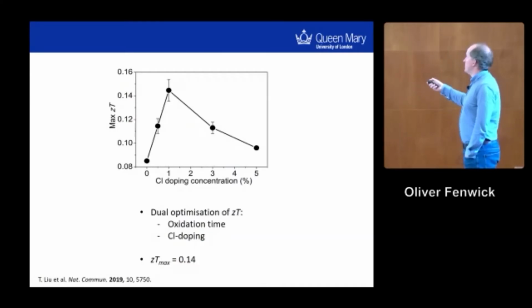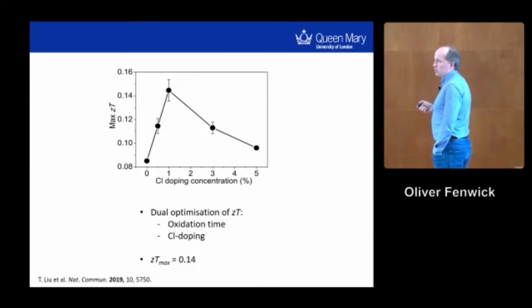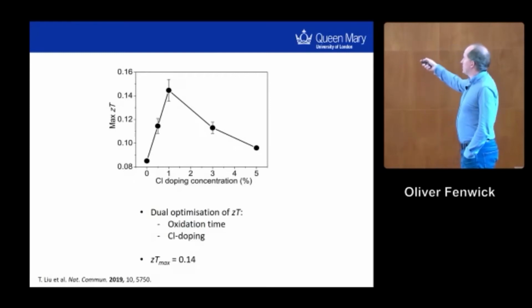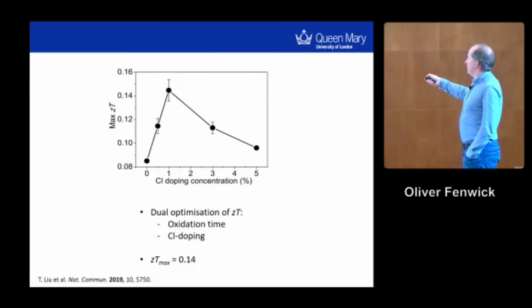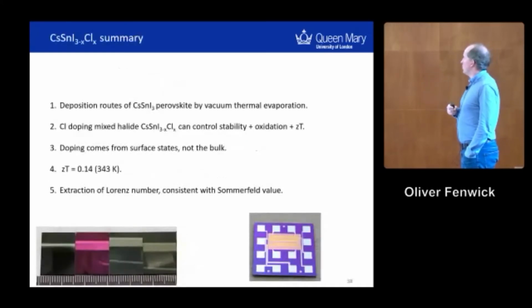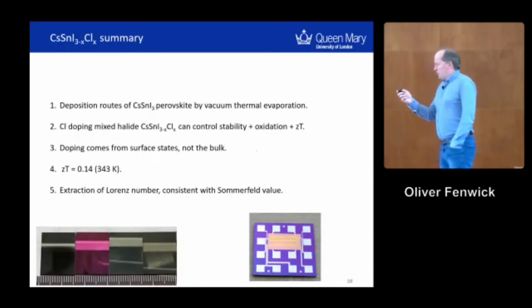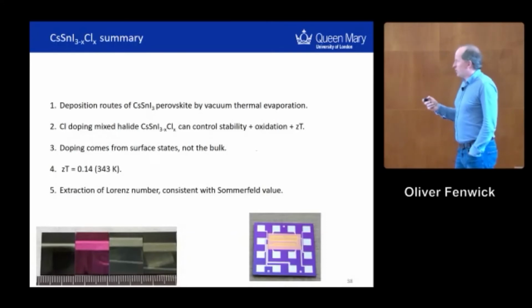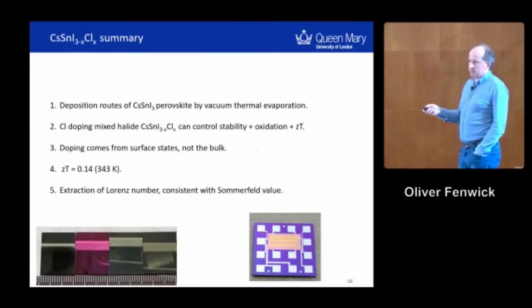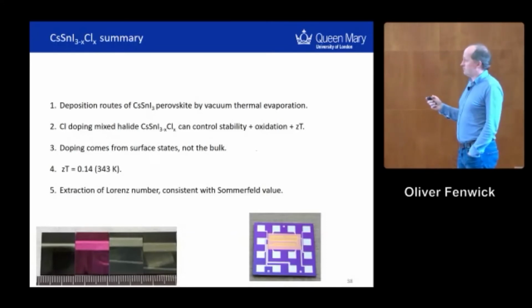Okay, so when we do this, we get to a ZT of 0.14. Very oxidation dependent, of course, and it's a dual optimization of the oxidation time and the chlorine doping, it turns out, as well. So that's a little bit more promising. I won't summarize that anymore, but there's some promise here, but we still have problems with stability, of course, being halide perovskite materials, but also with finding other systems where we can effectively dope them.